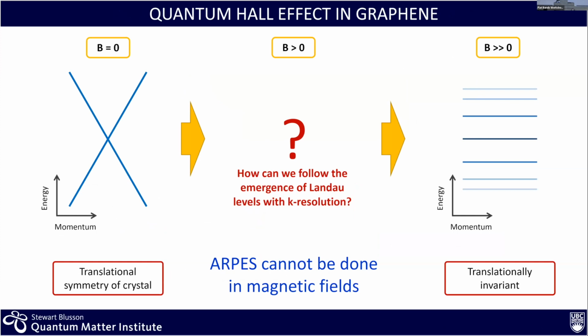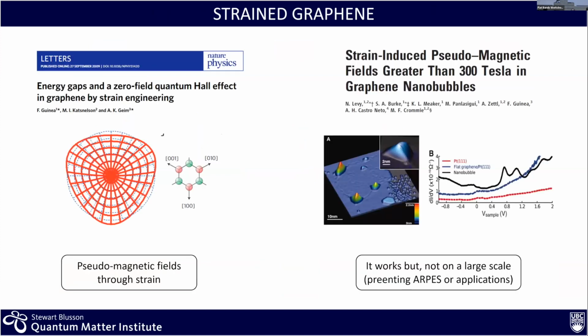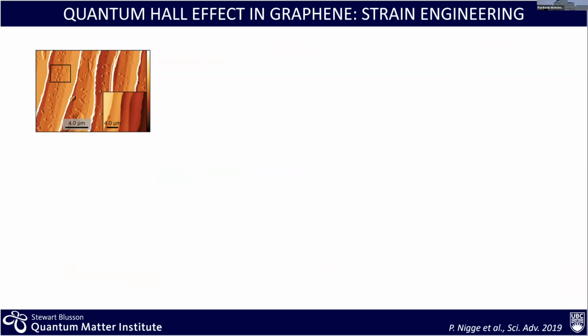And so here we try to do that through pseudomagnetic fields, so using strain as a way to induce Landau levels in your system. And the idea comes from the fact that on graphene, this is Guinea's work, very well-known work, where if you have a distortion of a proper symmetry, you can actually induce a pseudo field in your system, which can be as large as 300 Tesla, as seen by Crommie's group in graphene nanobubbles. Can we do that? And well, so here are our samples.